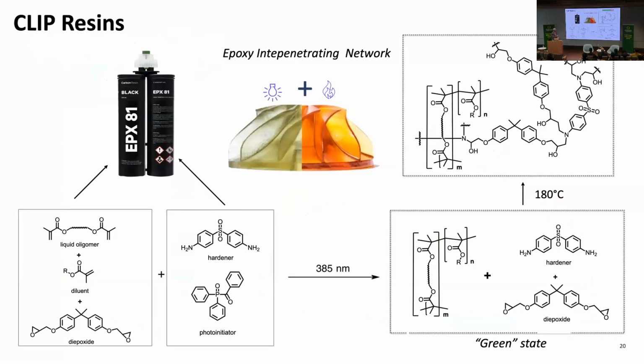So basically what we have is a free radical. About 15 volume% of the resin is free radically curable. And it's blended with polymers or monomers that form polymers via step growth polymerizations. So epoxy chemistry, polyurethane chemistry, cyanate ester chemistry. Here's an example of epoxy chemistry where we have a diepoxide and a diamine blended with a photoinitiator and a free radically curable system. You mix all these together from two different cartridges, and you print it at 385 nanometers, and this holds the part together.